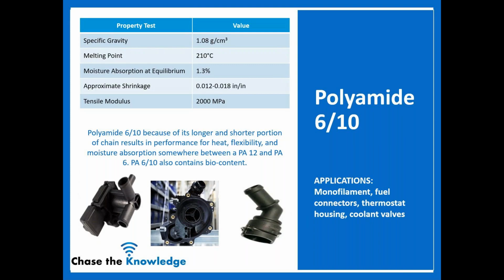The other thing that's nice about the 610 is that it also contains bio content. So maybe I'm looking for something in the middle for performance, maybe less moisture absorption than a 6, but higher heat than a 12. But then I also maybe need the sustainable solution portion of it. Maybe I need it to be a little green. So the 10 portion of that nylon is bio-based. And so it could be a good option for an application that needs something like that.